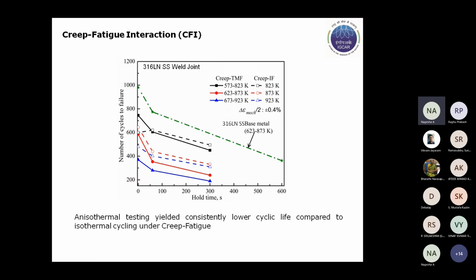And coming to the creep fatigue interaction, we have done a few tests on the conventional isothermal CFI, in comparison with the creep TMF loading, wherein we have incorporated hold times at the peak temperatures. We have seen that creep TMF shows a lower cyclic life compared to isothermal creep fatigue. You can see that for all the temperature ranges investigated, the creep TMF led to consistently lower lifetimes compared to the peak constant temperature creep fatigue.